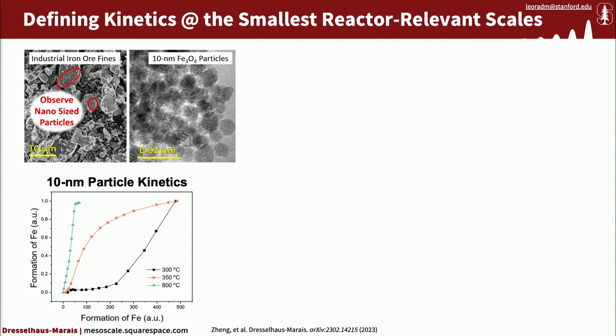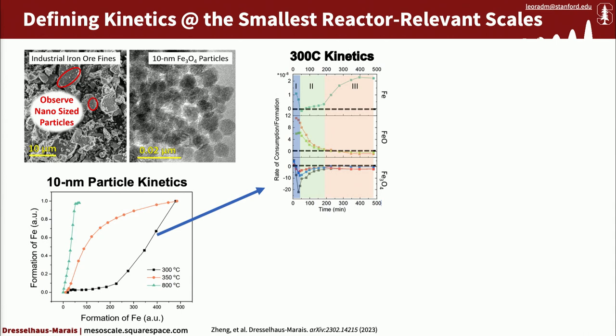So we went to the synchrotron and did an experiment, and we were able to show as a function of temperature that these nanoparticles really do behave quite differently at these unusually low temperatures. At the lowest temperatures, we could actually separate each of the steps of the chemistry. We were able to demonstrate that at 300 Celsius, first off, in the nanoparticles, you generate a phase that you wouldn't normally see until high temperatures. But second, we demonstrated that this breaks down into three different stages.